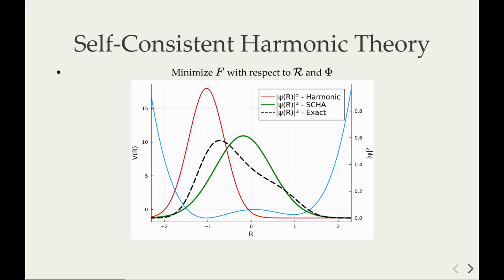Now you can see an example of the comparison between harmonic theory and self-consistent harmonic approximation in this double well potential, a strongly anharmonic case. In red, you see the result of the harmonic theory: we find the minimum of the potential, then we expand up to second order, and we solve the ground state of the harmonic approximation.